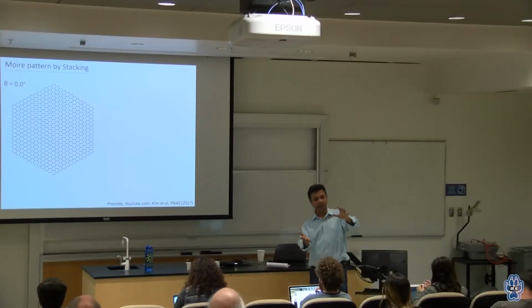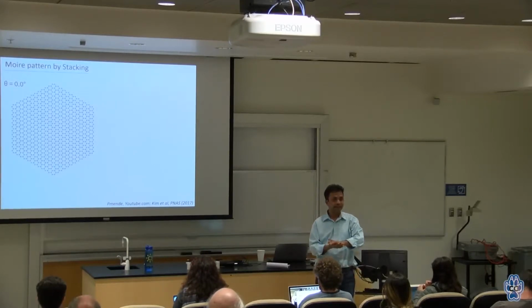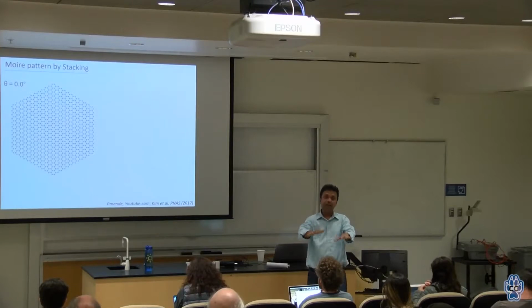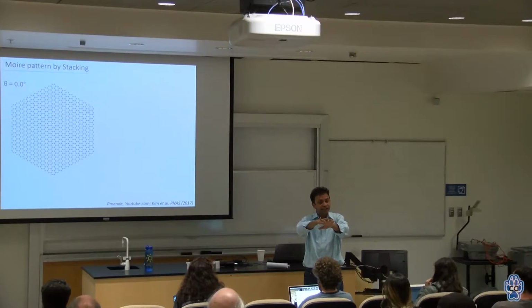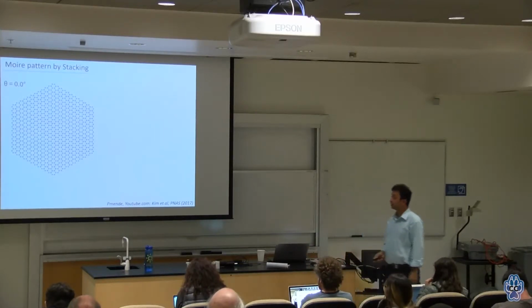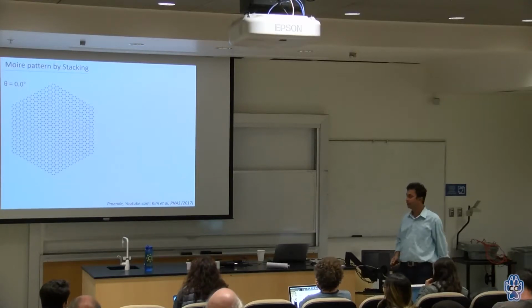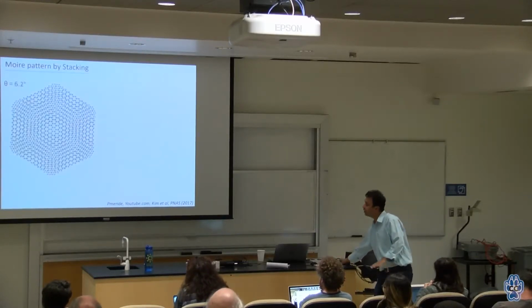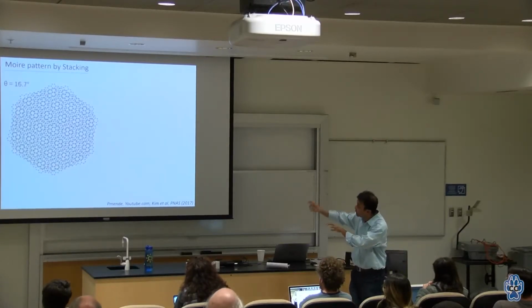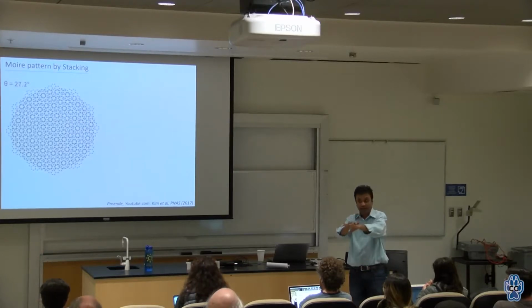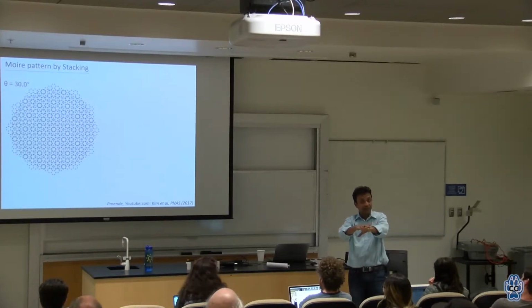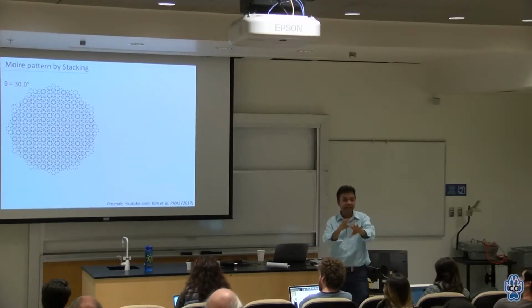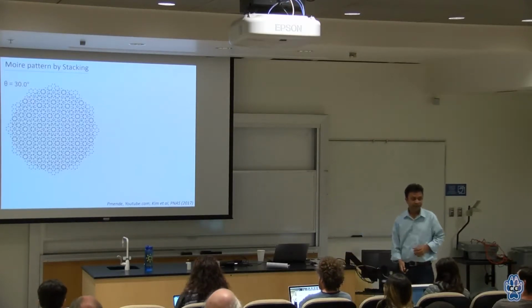So now I know how to put one material on top of another, right? What happens if I align two graphenes on top of each other? You can change the physical properties of the band structures of these materials, just make it so with the preferred orientation. For example, here is the image. You can see you have one graphene and the other graphene on top is moving. You see those structures appearing. You have carbon atoms with hexagonal symmetry, and then depending on the angle, you create another structure on top, right? That's called a moire pattern. All right.